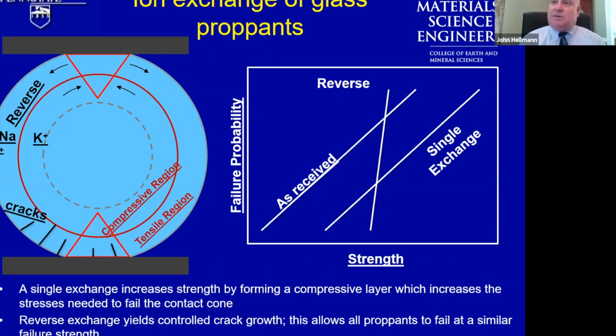This cartoon here shows you what the concept would be. That is, we would start with a proppant particle manufactured from glass in which we remove some sodium, replace it with potassium using a molten salt ion exchange process, and then using a reverse ion exchange process, put some of the sodium back. What this would result in is a tensile region at the surface and an embedded compressive stress field in the proppant particle, which would have a couple of benefits. The first is the inherent flaws at the surfaces of the glass particles would all grow to a finite uniform length. They would arrest at the boundary between the tensile and the compressive stress field, yielding a very highly reliable particle, high uniformity of strength, and potentially stronger as well.